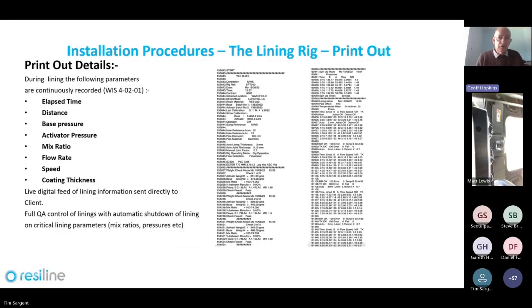Generally, the Drinking Water Inspectorate mandate what information needs to be recorded during a lining, which are these 7 parameters there that you see: time, distance, the material base and activator pressures, the mix ratio. If you know the pump flow rate and you know the pipe diameter and the speed that you're pulling it back, you know the coating thickness, because you have a volume divided by an area, which will give you a thickness. So that gives you the lining thickness that you have.